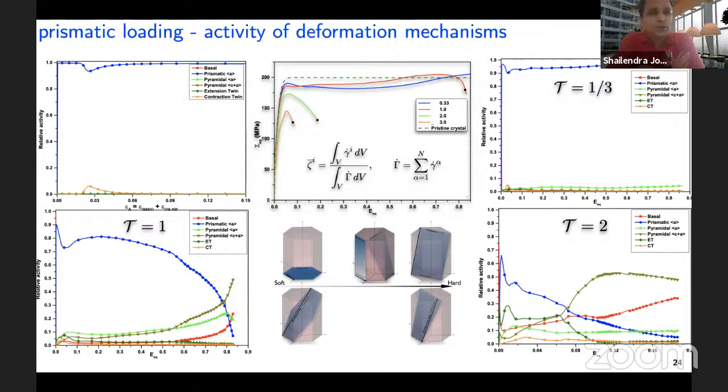I think what you're referring to in the context of more slip systems leading to more ductility is probably in the context of uniaxial loading, whereas what we are seeing here is a triaxial loading state. So the void is responding to the lateral stresses as well, and the higher the proportion of the lateral stresses to the primary stress, the more that will drive the void growth in the lateral direction, which is essentially what is going to cause the coalescence of voids.